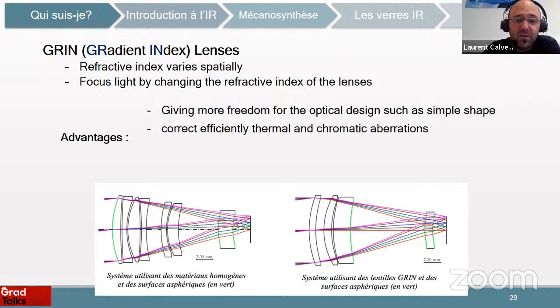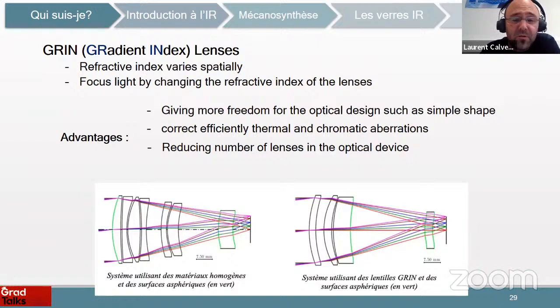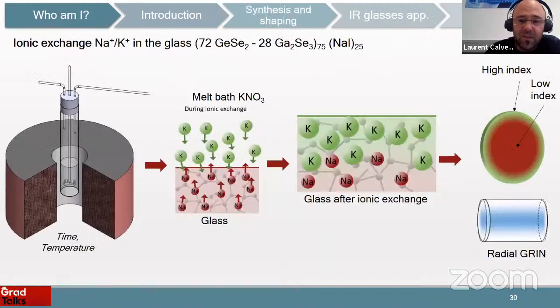You will be able to correct thermal and chromatic aberration, which means that you will have better quality images. You will also reduce the number of lenses in the optical device. As you can see here, you can get the same image quality using only 4 lenses instead of 7. So of course, you will lower the size, the weight, and the cost of the camera. How we can manage that in chalcogenide glasses is not so simple,